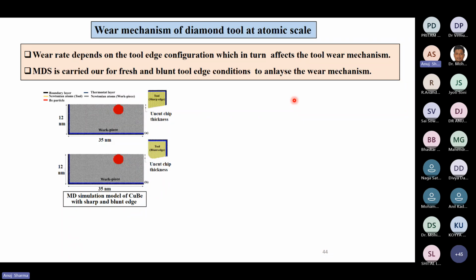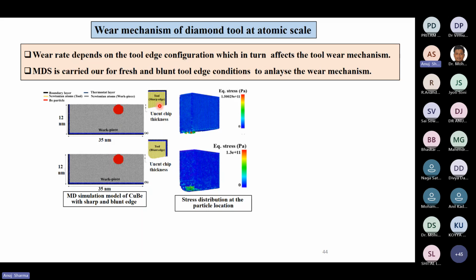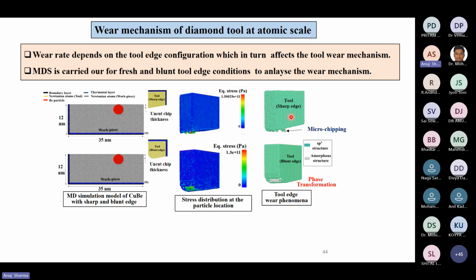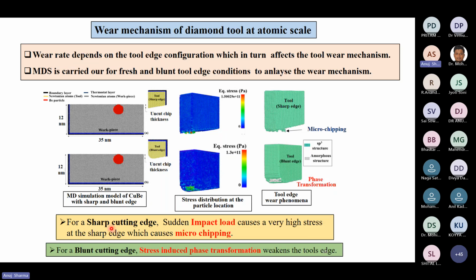So I tried to find out this difference between copper beryllium and copper for the tool using MD simulation. Here I took a sharp edge tool and a blunt edge tool, and the workpiece material was considered with the beryllium particle. It was seen that when the tool encounters this hard particle, the stresses were quite high at the edges. The structural analysis showed that microchipping was taking place in the sharp edge tool when it encounters the hard particle, and in the round cutting edge an amorphous layer was generated. That means phase transformation was taking place in the case of the round cutting edge. So it can be concluded that the sharp cutting edge, due to sudden impact load, experiences very high stress at the edge, which causes the microchipping. And in the blunt cutting edge, the stress induced phase transformation weakens the cutting edge.